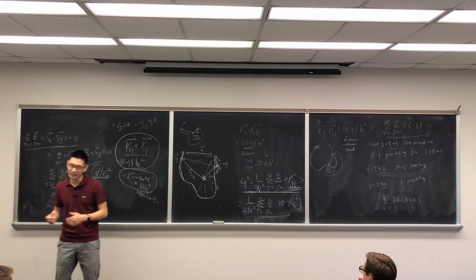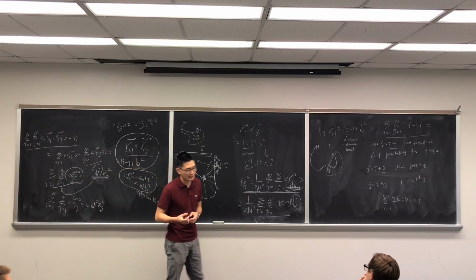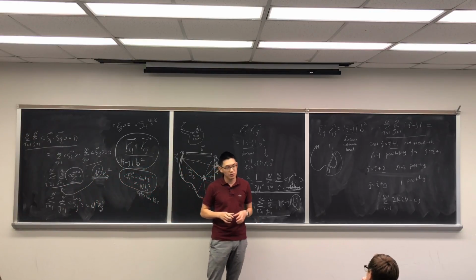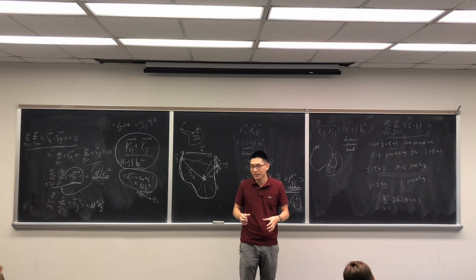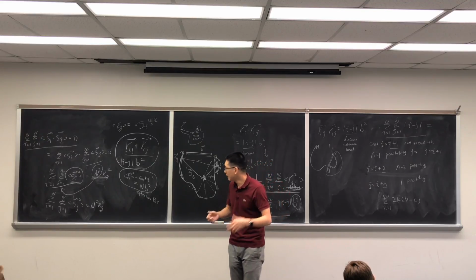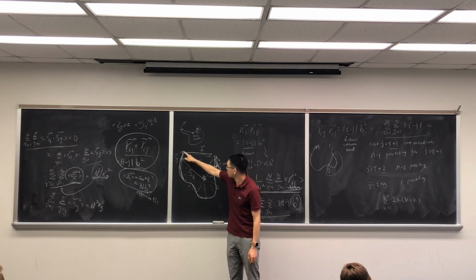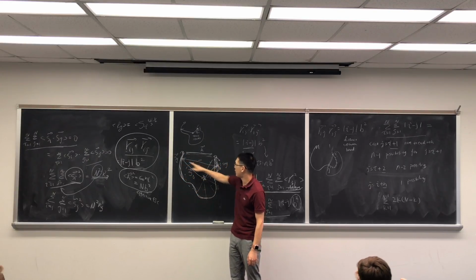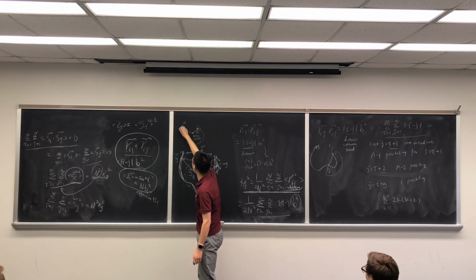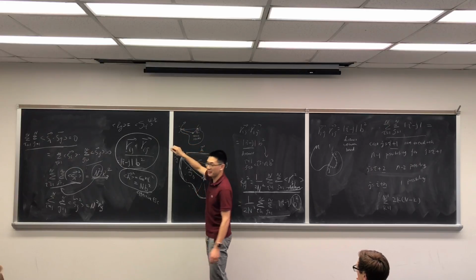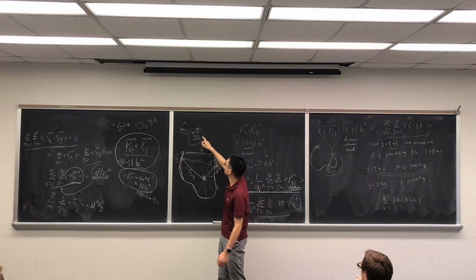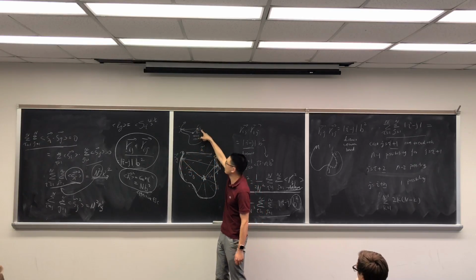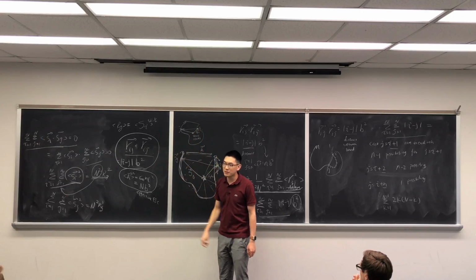Okay, so we're very close to the eureka moment, or why that's the relationship between them and why everything works out. If we look back at what we talked about in the class, we tried to use a triangle relationship to work it out, because any end-to-end distance only relates to the vectors along the bond. It's related to that Rij, right? So bonds I and J. That is what Rij is, and that's related to end-to-end distance. End-to-end distance is a special case of Rij when I equals 1, J equals N. That's basically the end-to-end distance.